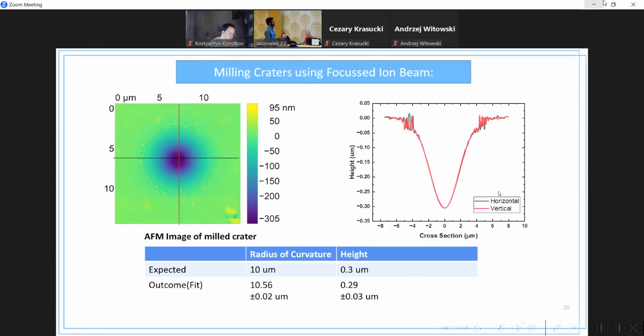Moving on, this is the AFM image of one of the craters that we milled. You can see this red and black line correspond to two cross sections of this image, and it's almost identical. There is almost no ellipticity present in this crater, and it's perfectly symmetric around the center.